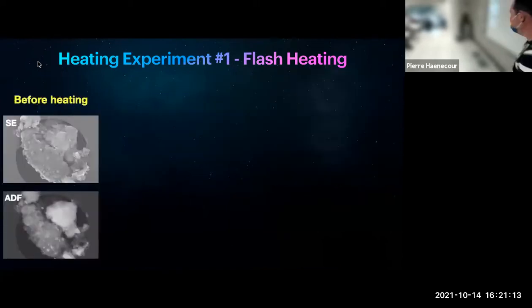Okay, so we do two different types of imaging live while we are heating. There is secondary electron imaging that basically gives you information on the surface of the sample. So you can see here what the surface of the sample looks like. And then we can do what we call bright field and dark field imaging, which is transmitted imaging. And so you can see through the thickness of the sample. That image shows you the inside of the sample, and the contrast is based on different types of elements.